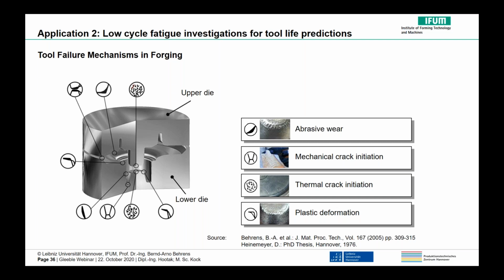So, in addition to an accurate material model, we also need to know more about tool failure to calculate tool life. State-of-the-art mechanisms such as abrasive wear, mechanical crack initiation, thermal crack initiation, or plastic deformation influence tool life in forging due to diverse thermo-mechanical loads. These mechanisms apply to thixoforging as well. However, the main loads are tribological, thermal, or corrosive.